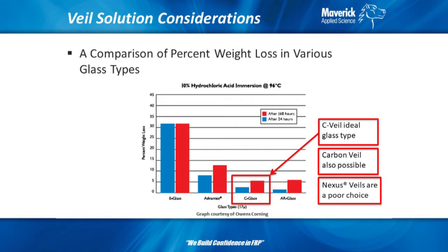What we see here, the C glass has the lowest percentage weight loss, so that would be the ideal glass type for 10% hydrochloric. Carbon veil is also possible. Like I said, carbon veil is not on this chart, but this is through our research and our experience. There are situations where you could probably substitute a carbon veil. Nexus veil is a very acidic, low pH situation. We just saw that on the chart earlier: low pH, not good for Nexus.